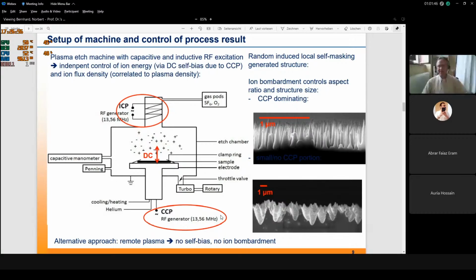You see here very high aspect ratio structures. Macroscopically, such a wafer is really black, and therefore such a surface is called black silicon. And the lower one is with more moderate aspect ratios. But both of these have the advantage over the wet chemical etch that firstly we achieve much higher reflection reduction, and secondly any kind of surface can be textured by this plasma etch process, whereas the wet chemical process needs already some pre-roughening for etch attack, whereas the plasma etch also works for absolutely smooth surfaces.